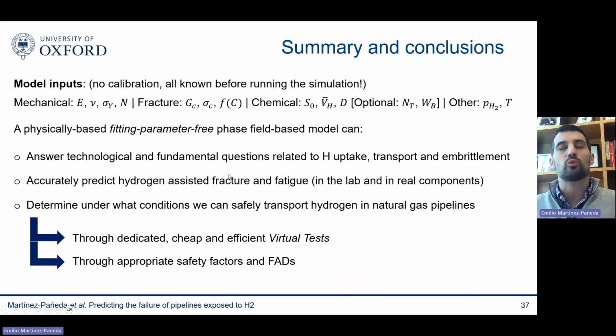But once you have these inputs, which are very well known, then you basically have a physically based and parameter-free model based on these phase-field methods that can not only answer technological and fundamental questions related to hydrogen uptake, transport, and embrittlement, but very precisely predict hydrogen-assisted fracture and fatigue, which is much more complicated, in both lab and real-scale components. And when we apply these to pipelines, what we see is that we can quantify precisely under what conditions we can safely transport hydrogen in natural gas pipelines.